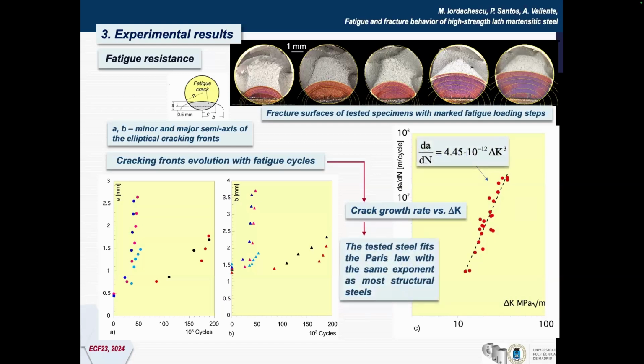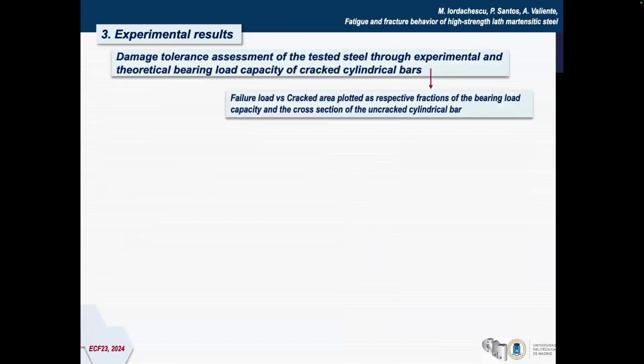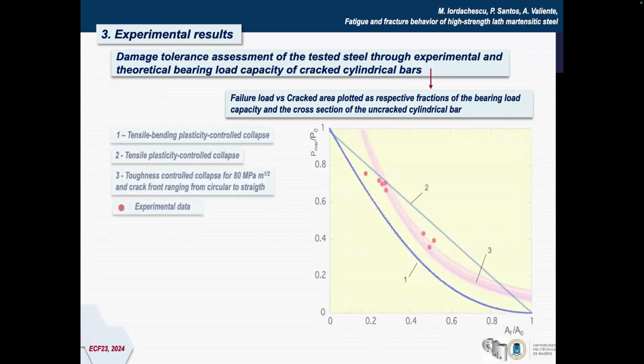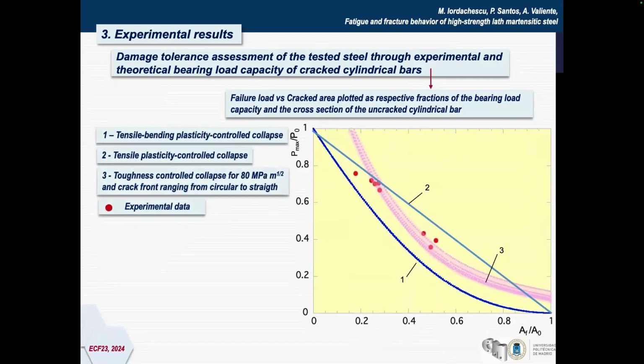And thus we obtained that the tested steel fits a Paris law with the same exponent as most structural steels that we are currently using in construction. Now, the last part is dedicated to damage tolerance, to a failure assessment diagram, which is plotted in terms of failure load versus cracked area.